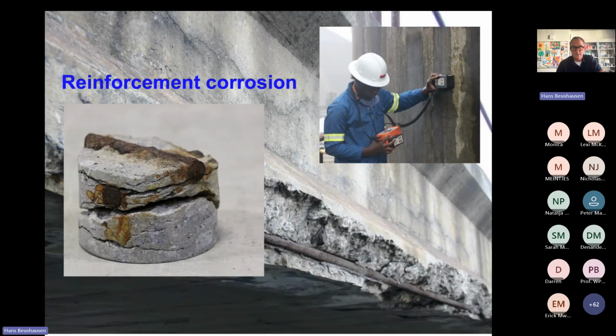And this core sample here shows you quite impressively how this rust development can lead to the internal damage that we can see on the structure in the form of delamination and spalling. As the rust expands further and further, it cracks open the concrete and leads to significant internal damage, which can, of course, then in the long term affect the structural performance of your structure.